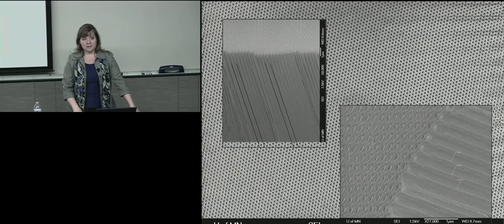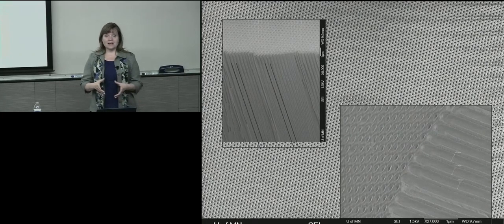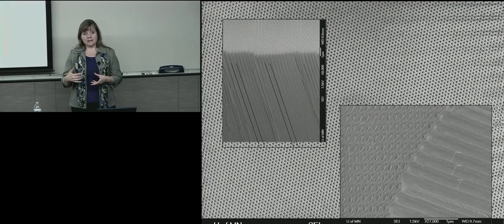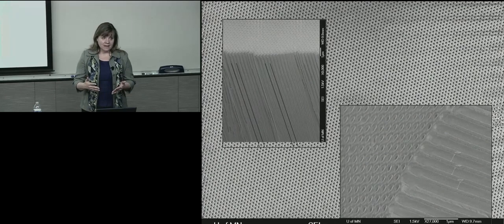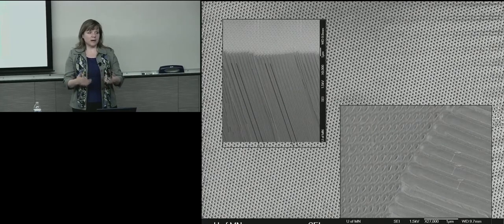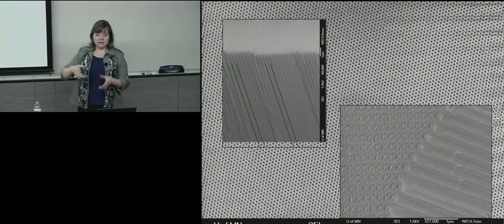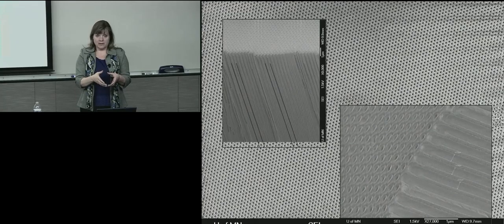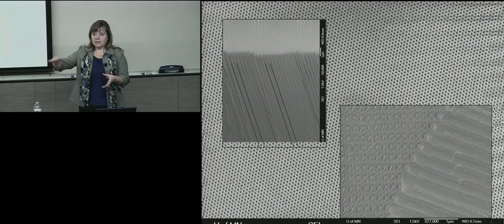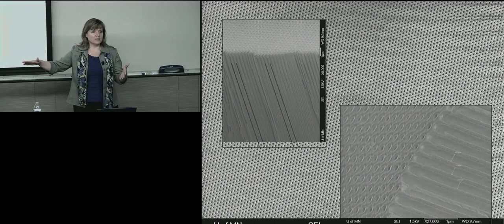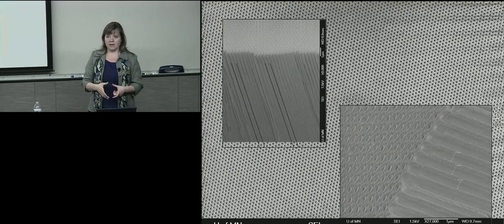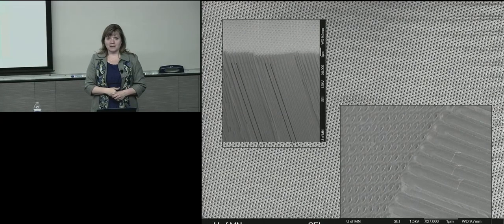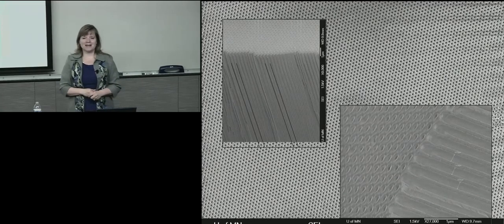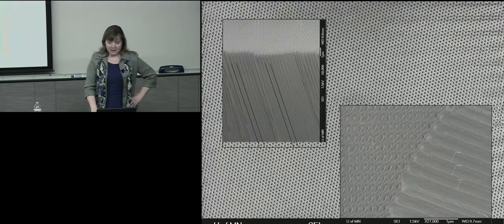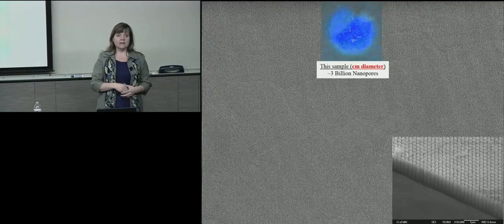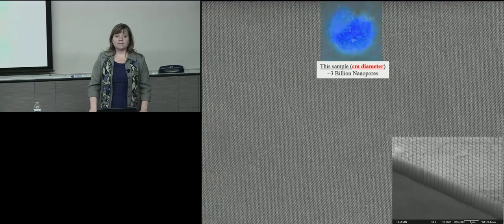Now, we've also gotten smarter that, as you were maybe already thinking, we now do an e-beam lithography in silicon, and we grow nickel on top of that. And we are good at electroplating now, so we can pop that off and use that as our stamp. So we can spend a lot on the master, make a lot of stamps, use each of those stamps lots of times, like 100 times. We can get a lot of samples out of one master. So to spend some money is fine, but 23 years is probably not going to happen, right? So instead, what we ended up doing is writing lines. Yeah? How many times can you use the stamp?